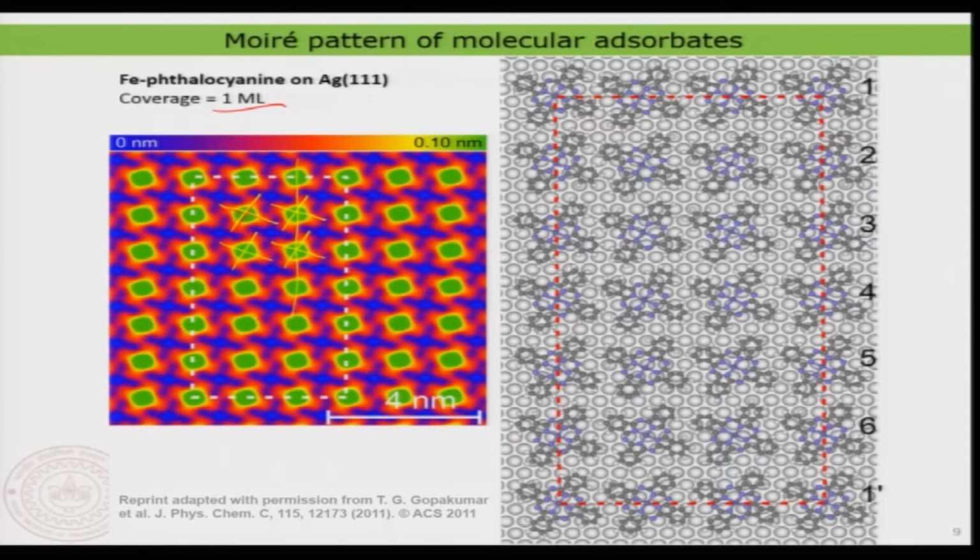So, this is basically the lattice, and this is the orientation of the molecule, about 30 degrees, for example. So, approximately 30 degrees is the azimuthal orientation of the molecule. That orientation comes from the fact that it allows the molecules to interact with the maximum surface area, because the intermolecular interaction in this case is a van der Waals type of interaction, and therefore the molecules always try to arrange in a way where there is maximum overlap between them. That is the basic key of this.